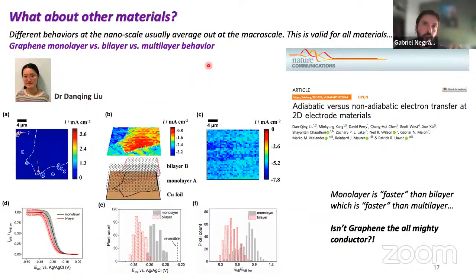So essentially, we did the same thing. We record CVs at every single location of a sample of graphene, which was composed of monolayers, bilayers, and multilayers of graphene. And again, similar to the ITO, we got a lot of different CV behaviors, right? So we can see here for the monolayer and the bilayer how they are slightly different. So we get a mix of behaviors with different kinetics, faster and slower kinetics.